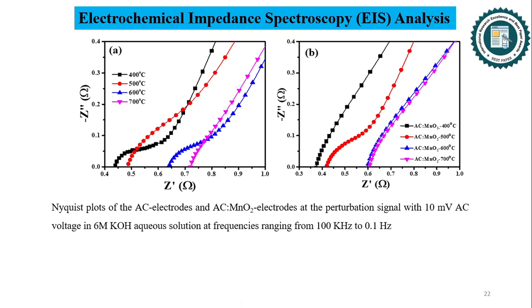Notably, AC 400 degrees centigrade electrode demonstrated superior conductivity with remarkably lower internal resistance of 0.43 ohm compared to other activated carbon electrodes, attributed to its higher specific capacitance, facilitating efficient ion and electron movement. Among the hybrid composite electrodes, AC MnO2 400 degrees centigrade stood out with significantly lower resistance of just 0.36 ohm compared to AC 400 degrees centigrade, attributed to its high specific capacitance, enhancing ion transport and conductivity.